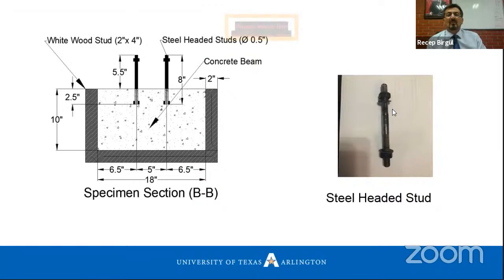And these are the anchor bolts we used. We use a steel-headed stud. As we see, we have a head at the bottom here, just to increase the concrete breakout strength. And we make sure that the distance between anchor bolts is less than 3 times the embedded length, so that we have a grouping action at this region. We need to see how much that will affect the strength of the anchor bolt individually.